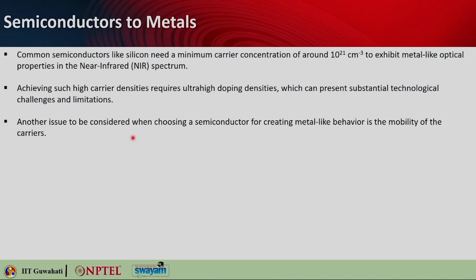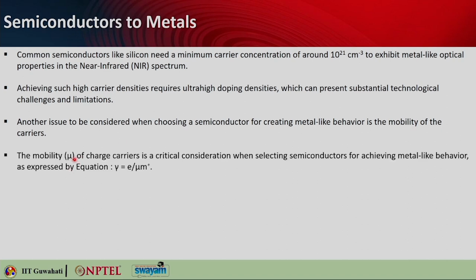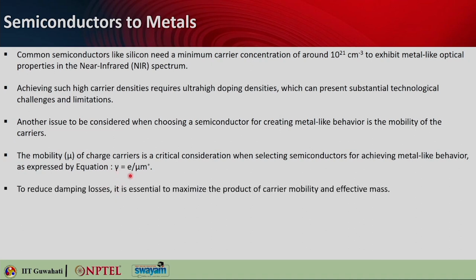Another issue to be considered when choosing a semiconductor for creating a metal-like behavior will be the mobility of the carriers. Okay. Now, the mobility mu of charge carriers is a critical consideration when you want to select semiconductors for achieving metal-like behavior. This is the equation that correlates mobility with the other parameters. Okay. So, you can see that gamma equals e over mu m star. So, to reduce the damping loss, it is important to maximize the mobility and effective mass product. So, the denominator should be as high as possible if you want to reduce the damping loss.